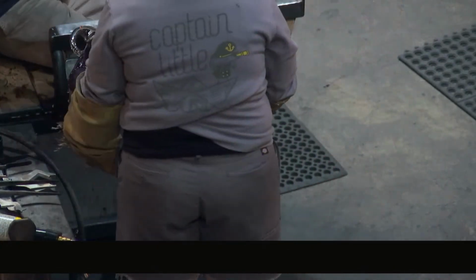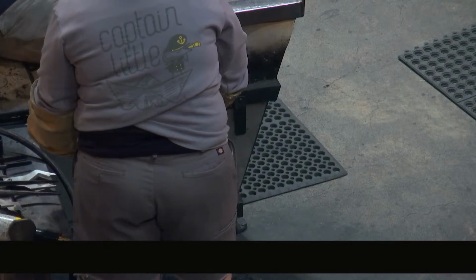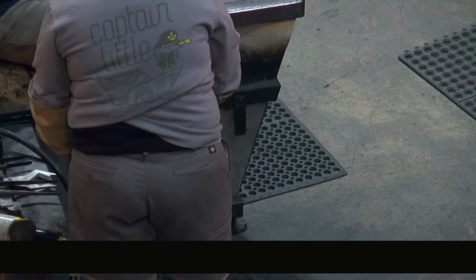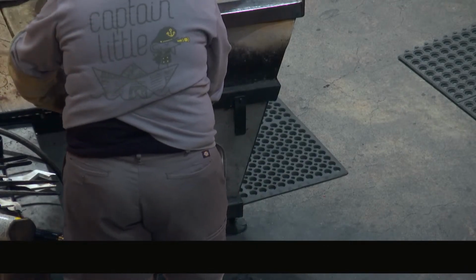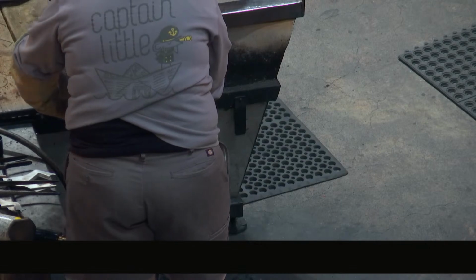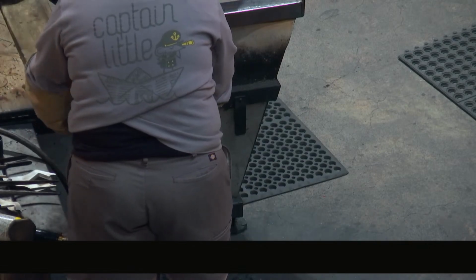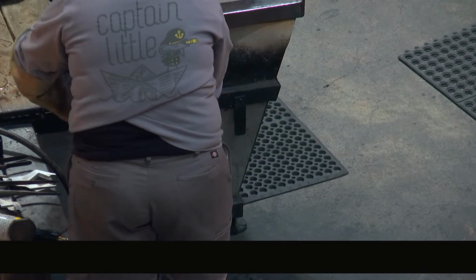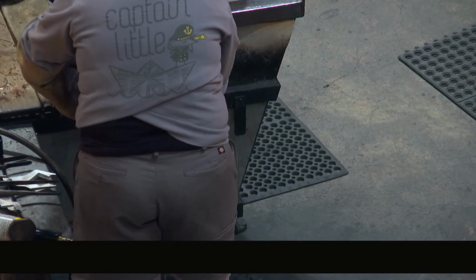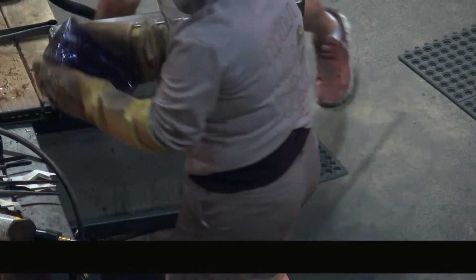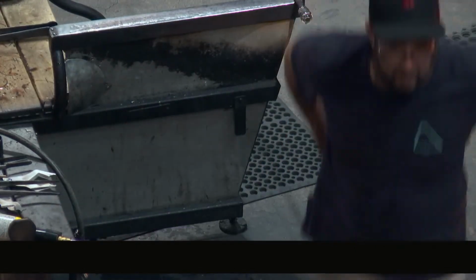And now to break this little pitcher off, all they have to do is apply some water to that small connecting point right at the end of the pipe. This is causing just a little bit of shocking and cracking in the connection, and then they tap the pipe and that breaks that piece cleanly off. Looks like that was a successful break.